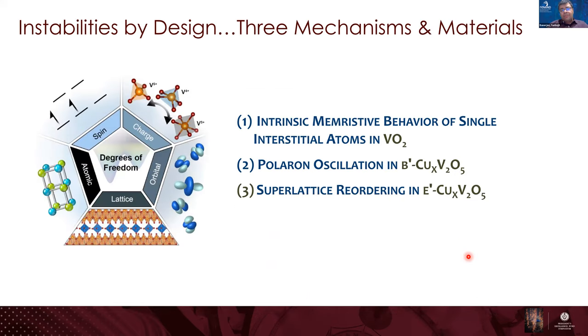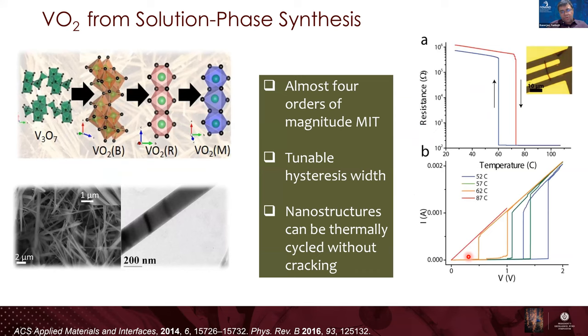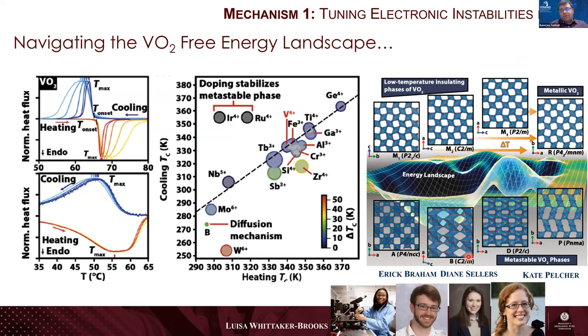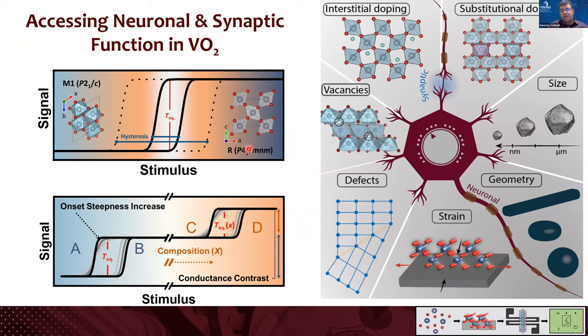And so that brings me to some mechanisms we're trying to discover. VO2 has absorbed a lot of our interest. Okay, so we've got this four orders of magnitude MIT, we could tune hysteresis, and so on and so forth. And we've sought to navigate this energy landscape through alloying, because the idea is could you essentially modify the nature of the transformation, and by modifying the nature of the transformation, make it less lattice and more Mott transition, right?